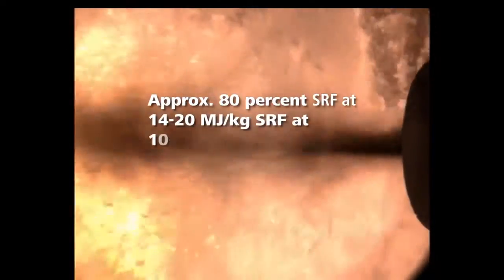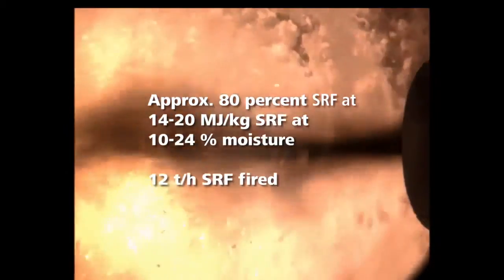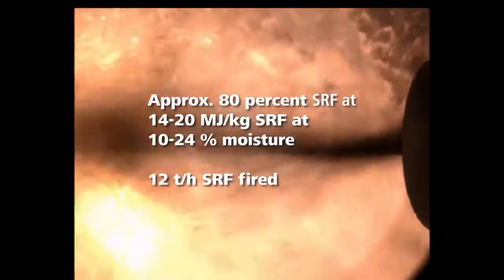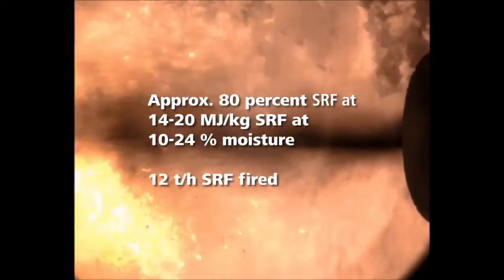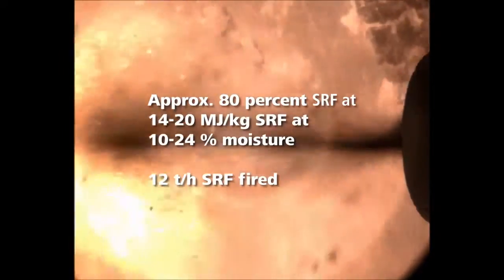Following the kiln startup, a series of tests were performed to observe the JetFlex burner's ability to burn conventional fuels and alternative fuels. The JetFlex burner showed a well-defined fuel distribution pattern and the coarse SRF was suspended for longer in the flame core. Optimal positions were found for the air nozzles and fuel substitution was gradually increased while maintaining good clinker strength.